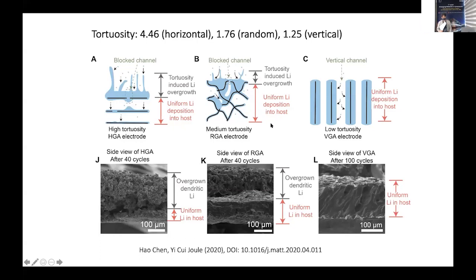If you look at tortuosity, we measured it. Horizontal align has high tortuosity, about 4.5. Randomly aligned is about 1.8, but vertically aligned is about 1.2, 1.3. So this is a very strong correlation of tortuosity affecting the plating stability.